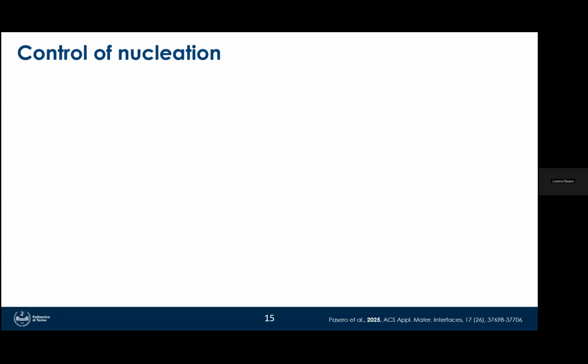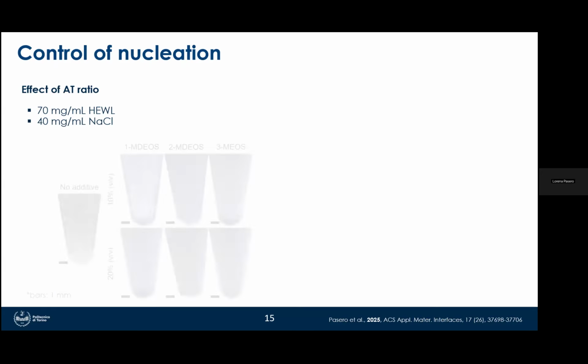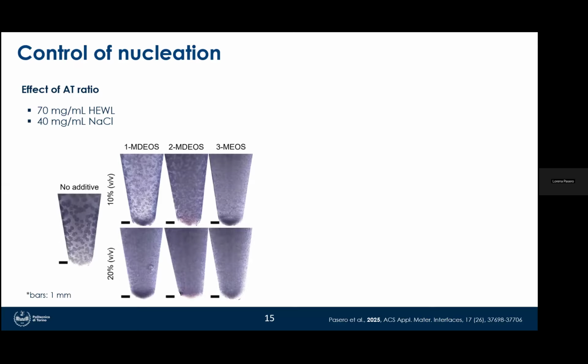So once we selected the optimal content of tetramethoxysilane, which was 10%, we investigated in the next part the effect of the additive to silica ratio. We selected a combination of protein and salt of 70 milligrams per milliliter of lysozyme and 40 milligrams per milliliter of salt. And the AT ratio was kept at 10 and 20%. So here we evaluated how the incorporation of additives altered the crystallization and so the nucleation.